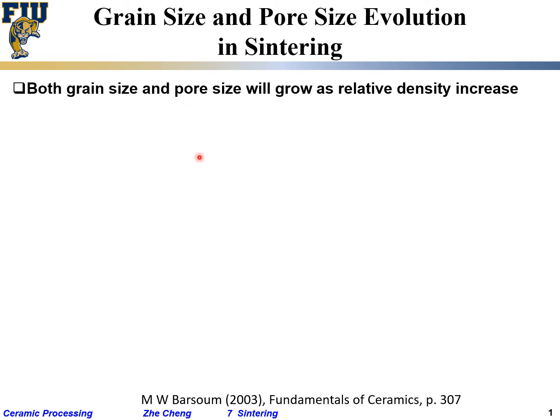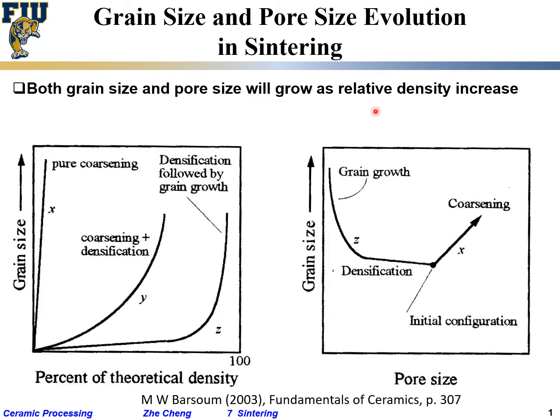Here we are going to talk about the change in grain size — how big is an individual grain — as well as pore size during the sintering process. Both grain size and pore size, where pores are essentially between the individual grains at the corners, will increase due to coarsening and the grain growth phenomenon as relative density increases.